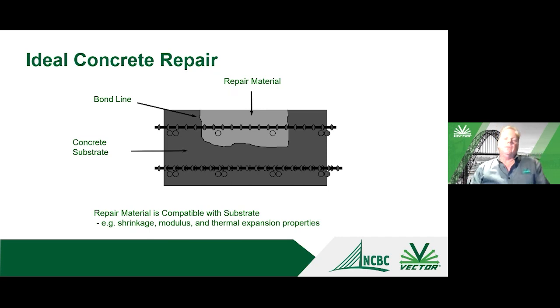So you look at concrete repair, and I think most people start off by learning about concrete in the context of new construction. I think we need to look at concrete repair a little bit differently, where the repair itself is really in a confined condition. So we're going to do everything we can to have a good quality surface preparation and get good bonding, so the material itself is confined. So we start looking at the repair material properties, and things such as a 10,000 psi concrete or concrete mortar may not be the best thing for the structure. You may have high cement contents, and you could have any type of cracking, plastic shrinkage or drying shrinkage cracking of the repair material, which will limit the repair's durability.